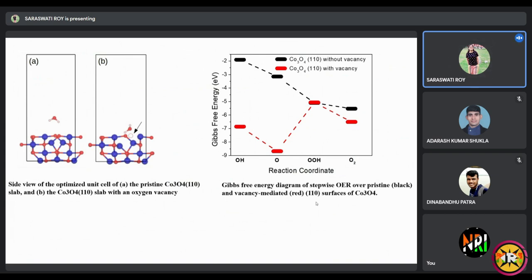This is H2O. Basically, I have told you OER is happening in alkaline medium or in acidic medium also. So basically H2O is converting to O2. That's why we have taken H2O coming towards your catalyst. So in figure A, when oxygen vacancy is not there, the attraction is very less, but when the oxygen vacancy is there, if some oxygen is coming out from your lattice, that means first oxygen formed a bond with cobalt. If one bond is breaking, that means there is less hindrance in your synthesized compound. So OH or H2O can come easily towards your catalyst. Okay. That we have shown from DFT calculations.